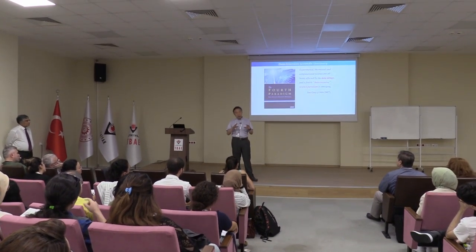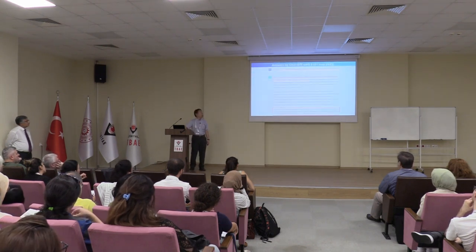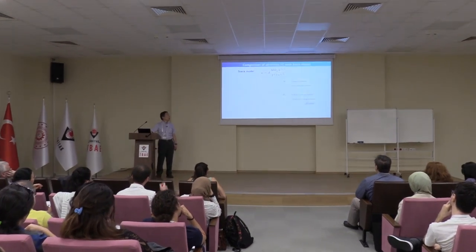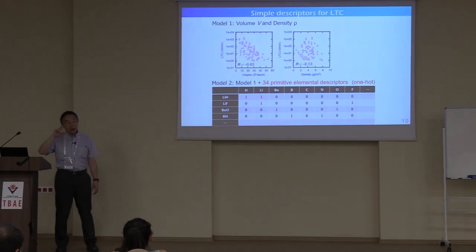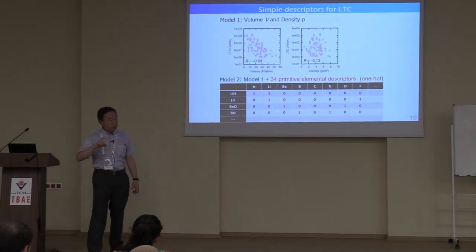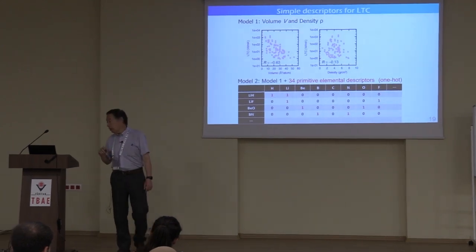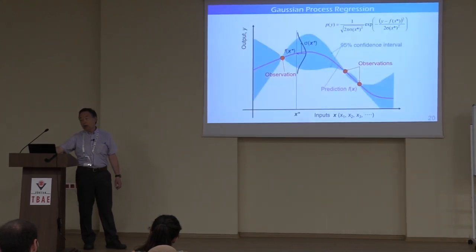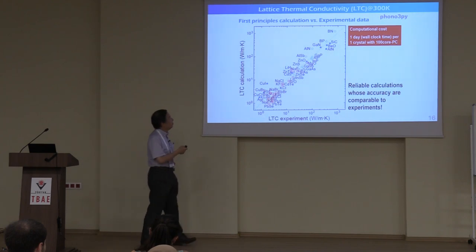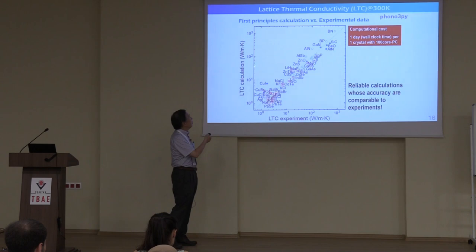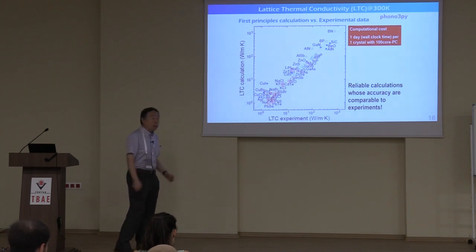But because this model was too simple, we tried to improve our model. And actually, we succeeded in making a better model than this one. Of course, this is too simple. We also estimated the error by this model and by the other model. The other model uses many more meta features than this one. And the result is the error was much better. Here the error by the previous model was something like this amount, like 0.5 in logarithm scale. But if we improve the model, it becomes 0.1. So it's 5 times smaller error.